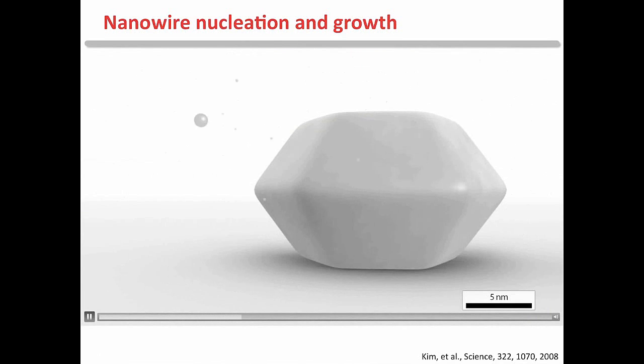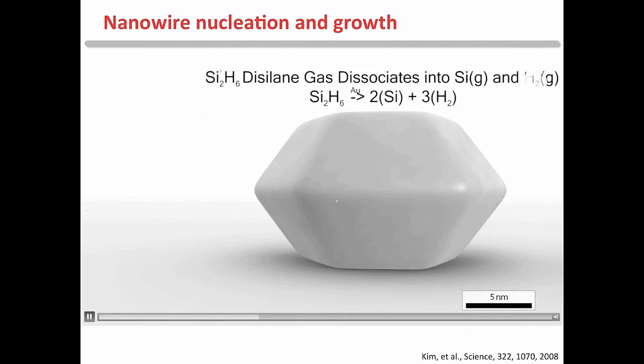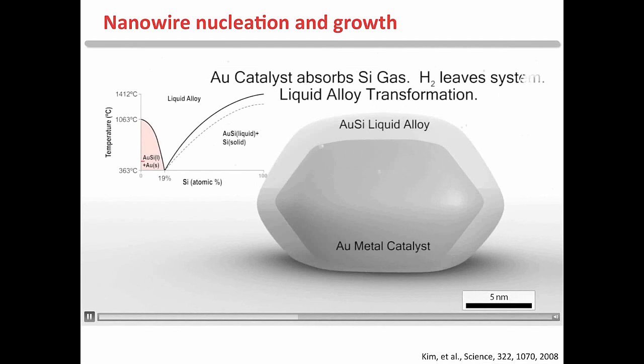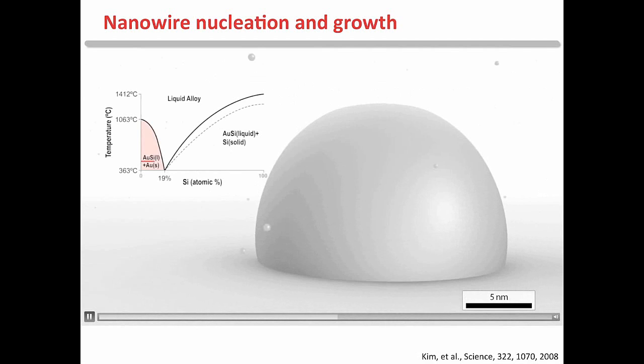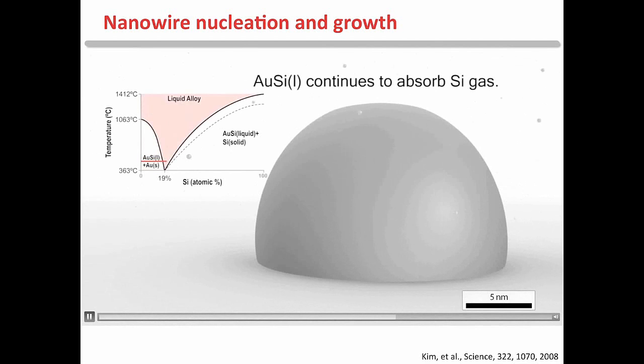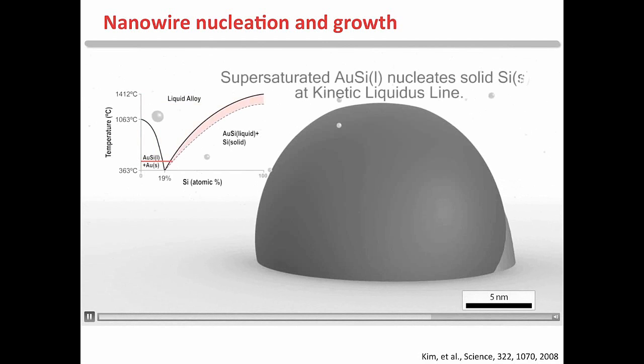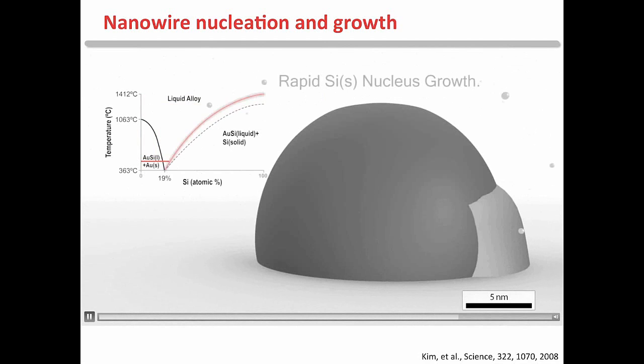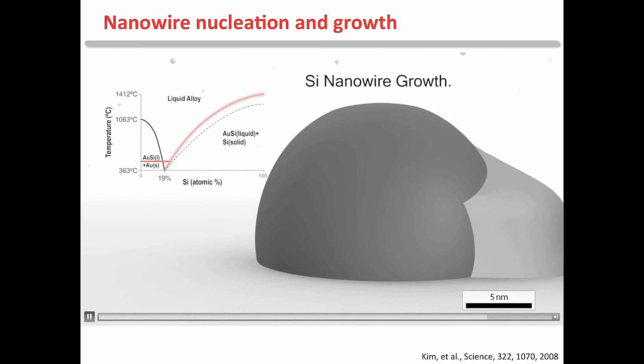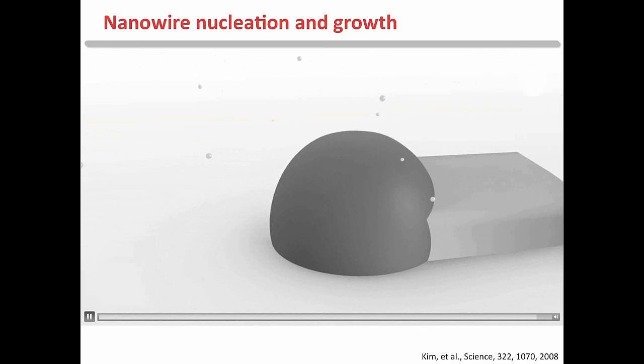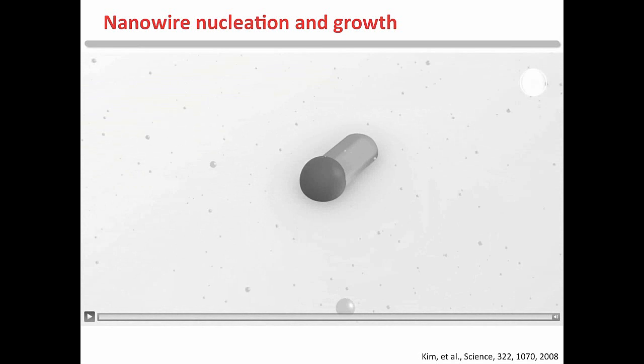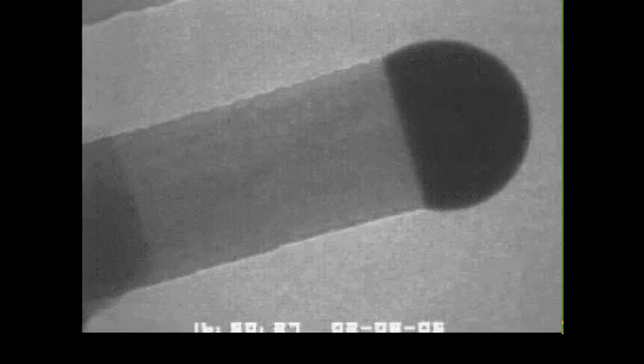The idea is the disilane comes in, dissociates, and then begins to gradually incorporate. This liquefies first the outer surface, then eventually the whole material. And as you incorporate more and more silicon into the alloy, it's fully liquefied. And then at some point it actually supersaturates. At the point of supersaturation, you see nucleation and growth. And again, if you do this on an amorphous substrate, the nanowire crawls off and moves off to the side. If instead you do this on an oriented substrate, what you see is these nice nanowires growing in a directed mode.